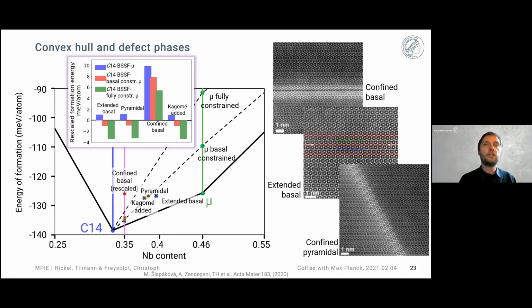And that means we do understand that adding niobium, that means changing the chemistry, completely changes the defect state. You have niobium-rich defects, and it changes the stability of this defect. And this is a completely new understanding now of thermodynamics. You have to make phase diagrams and thermodynamics for defects, taking care of the chemical and temperature degrees of freedom.